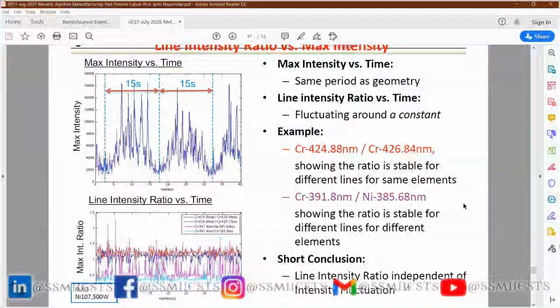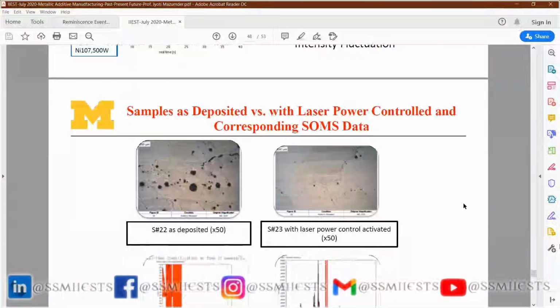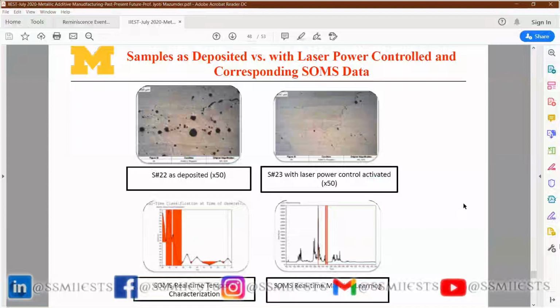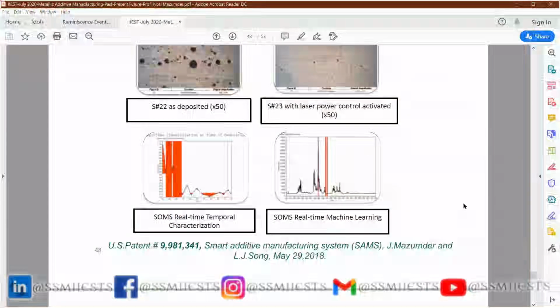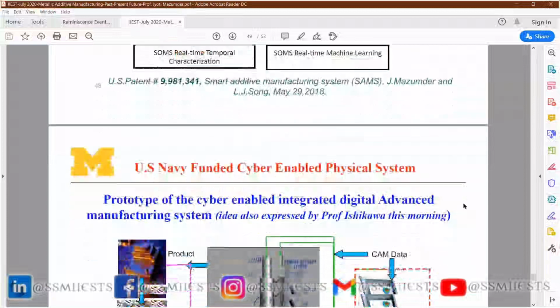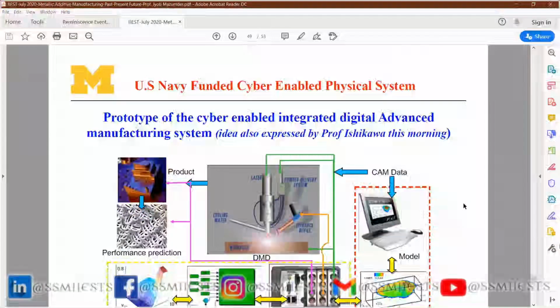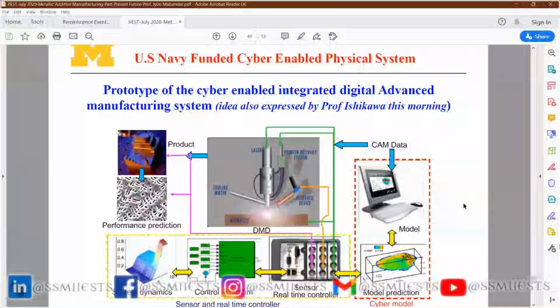The last but not the least, trying to stay within the time, we use that information. There is the advantage of being a metallurgist in a mechanical engineering department, that I also have colleagues who work on all kinds of controls and other things. And what we found is that I take that information, feed it back into the 3D printing system, and by doing that, I can remove the defect before the production is complete. Now, this is the real-time temporal characterization. We got it, and then with the feedback loop, when you run it, most of the defect is gone.